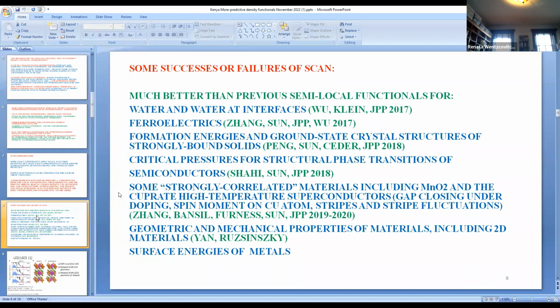SCAN by itself, without any correction, is also good for some strongly correlated materials that standard density functionals normally do not get right, including manganese dioxide, which has many different crystal structures, and also the cuprate high temperature superconductors, where we get a fundamental energy gap in the pristine material, and as we dope the material it transforms from an insulator to a metal.